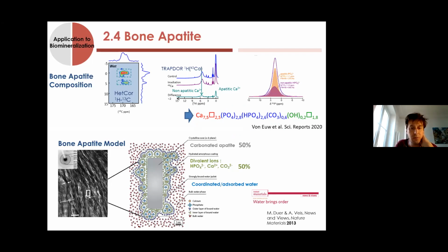The model of the particle is composed of 50% carbonated apatite in the core of the platelets, and an amorphous domain at the surface, which is quite important in terms of proportion, composed of divalent ions and, of course, a lot of water around.